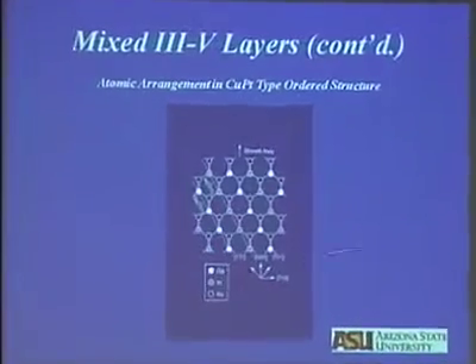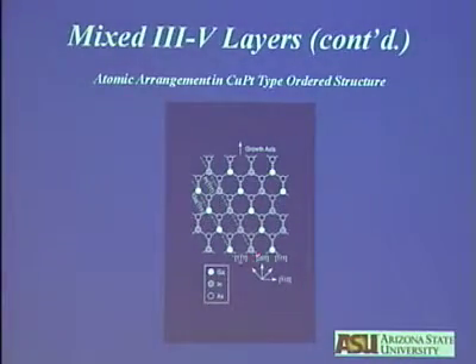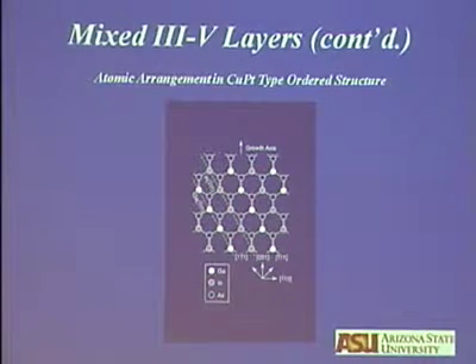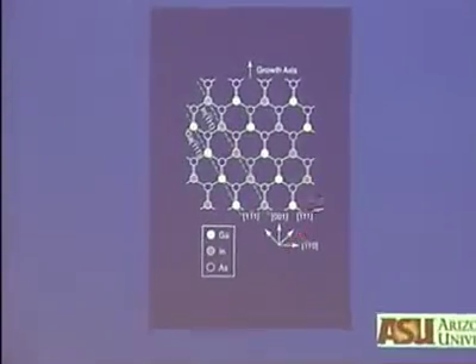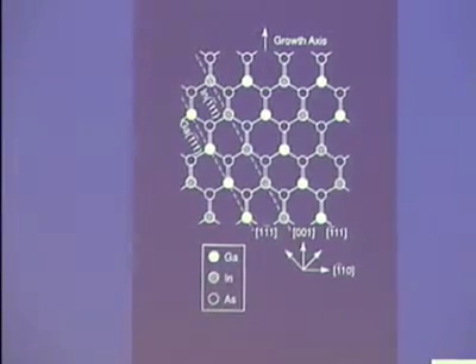This is a 110 section again, as this is the growth direction. Coming out is a 110, this bar, 1 bar 10. And the arrangement of the 111 planes in the zinc blende lattice is AA, BB, CC, just like the FCC lattice, but now you have two interpenetrating sublattices, so you get AA, BB in this structure. Now, capital A becomes a gallium-rich layer. Then the next one is your group 3-5. Then the next layer is an indium-rich layer, and this repeats. And if you look at the periodicity along this direction for this case, you will see it is double. So ordering occurs on only two of the four 111 planes.